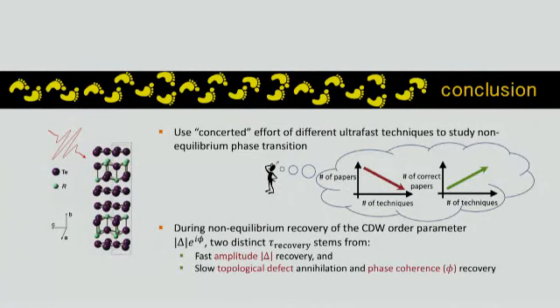Also for the phase mode, if you compare phase fluctuation to amplitude fluctuation, the phase mode in these incommensurate charge density wave materials is gapless, so we can easily populate low-energy-lying phase states, whereas the amplitude mode actually has a gap. So in terms of energy cost, it's easier to excite the phase fluctuations than the amplitude fluctuations. That's one idea we have.